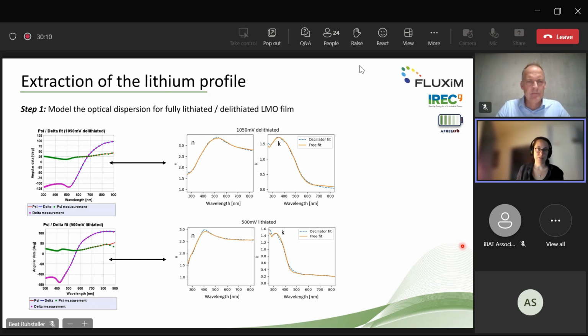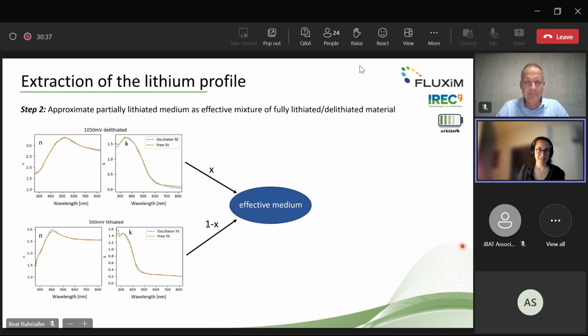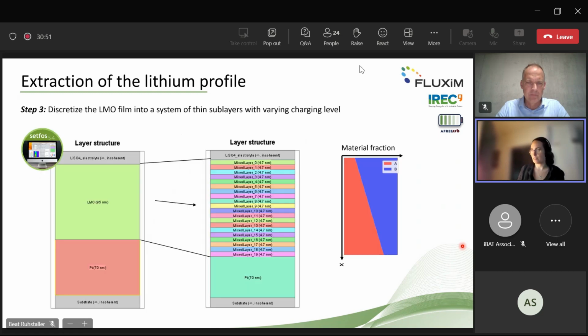And now the model works as follows. First we have to understand the composition of the fully charged or fully lithiated and delithiated LMO film. Basically, this was done here, to obtain these optical parameters N and K for both states. Then one can use this input data and, on the next slide, mix these two materials together with a so-called effective medium approximation. So we use a certain fraction x from the delithiated state and 1 minus x of the lithiated state to get an effective medium. And to parameterize this in the z direction, we made small layers, and in these compositions we fixed the ratio x, and by this you get a profile over the position in the LMO layer.